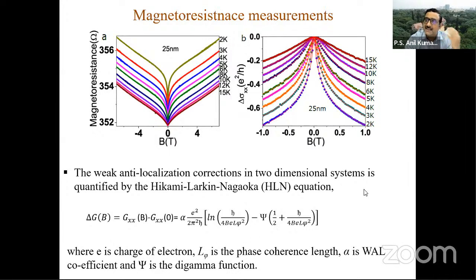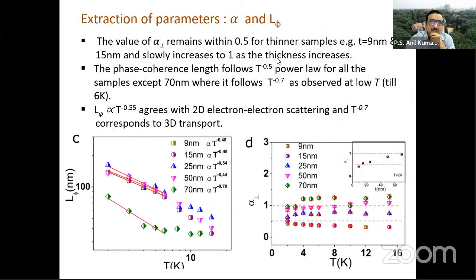Now for different thicknesses of this film, if you look at the alpha and L_phi, we see that when you make the thickness extremely small, like say 9 nanometer, this alpha is going to be 0.5. That tells me that the surface states are all interacting with each other, and you get a single channel of conduction. But if I increase the thickness above a certain point, you see decoupled surface states here.